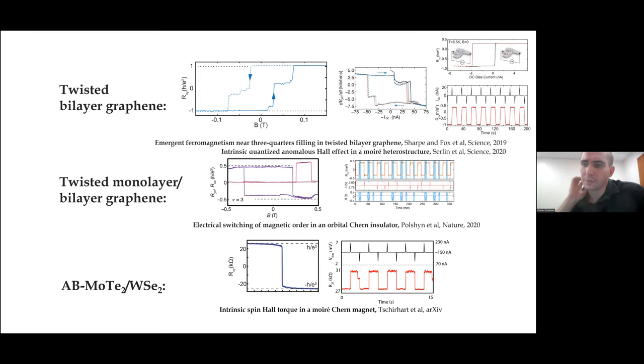As before, I think it's worth mentioning that all of this is happening because the magnetization contributed by spin, contributed by other channels like magnetic dopants, is modest relative to the magnetization of the bands themselves. Generally speaking, as long as you avoid the limit where the magnetization is dominated by magnetic dopants or by some higher energy scale than is producing the exchange gap of your magnetic Chern insulator, these phenomena should be general, right? So you should see spin Hall torques and, for Chern minus one ground states, switchability of the magnetization through coupling to the chiral edge states in any Chern insulator, in any Chern magnet.